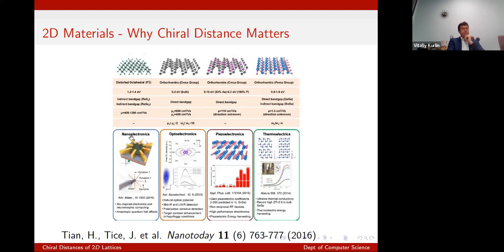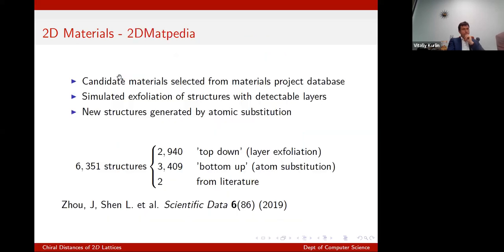There are lots of ways to get asymmetry. Some aren't to do with the lattice — they're about materials not being truly two-dimensional, with asymmetry living in the depth. But there are also MX2-type materials with genuine 2D lattice asymmetry. I'll be using publicly available 2D materials databases. 2DMatpedia is interesting: it's highly theoretical, taking bulk 3D crystals and using a topological procedure where you grow unit cells and measure connectivity — a 2D layer grows as M², a 3D structure as M³.